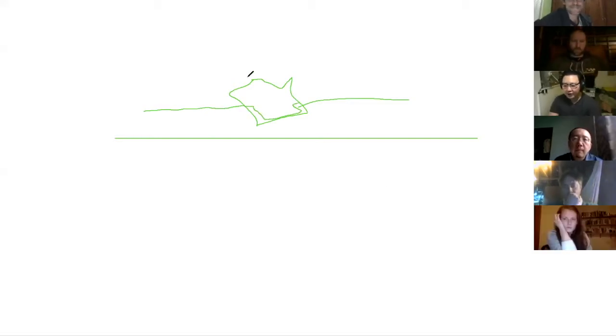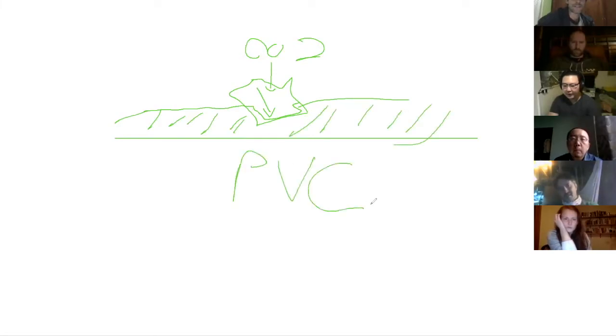Maybe it'd be helpful, I'm going to screen share to draw what I'm asking. If this is the support material, and let's say there is a jagged piece of the resin that has been ground down, then there is some sort of adhesive that is going to make this portion of the resin inaccessible to atmosphere, right? So if this has CO2 over here, will it absorb into the entire volume of the portion that's embedded? Because this would all be hidden by the adhesive and the PVC. So it will diffuse through the volume of the resin? Of course, because there are also some beads inside the PVC. I see. Yeah, most of the powders are embedded inside the PVC.